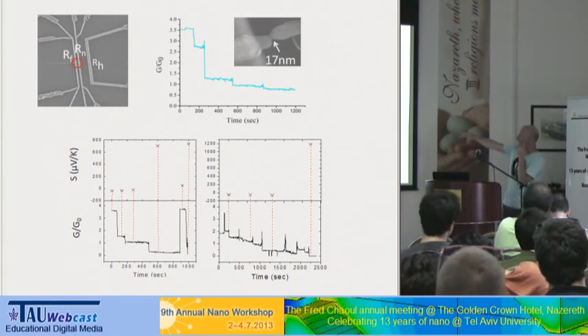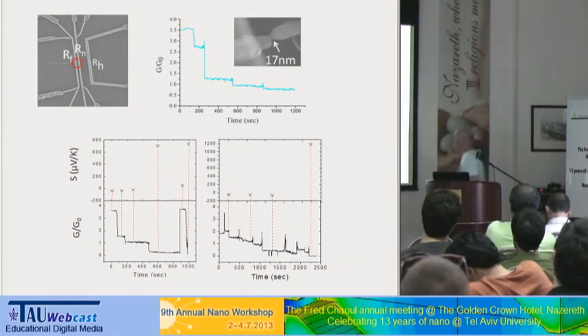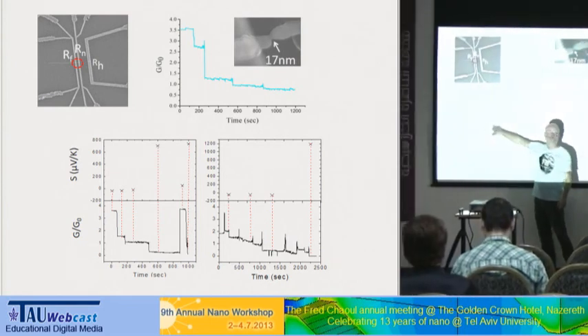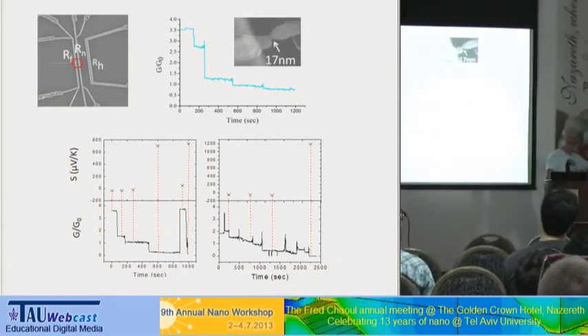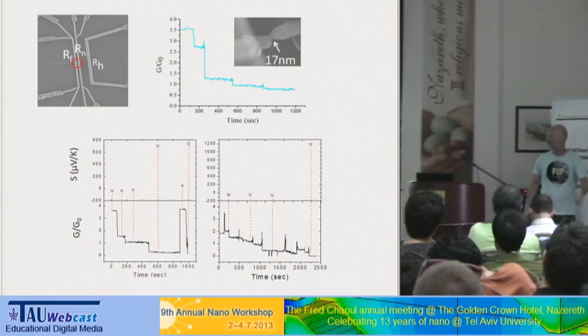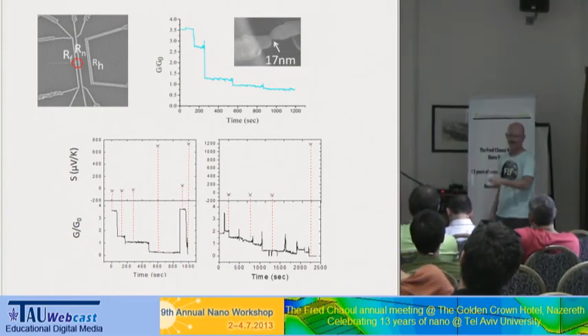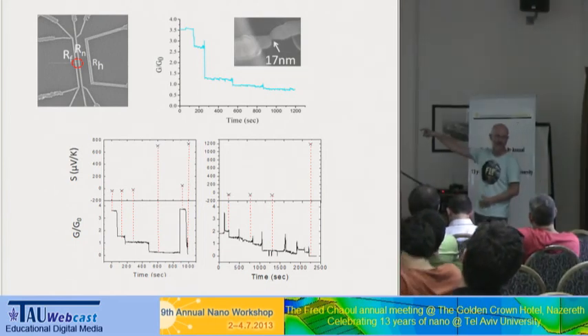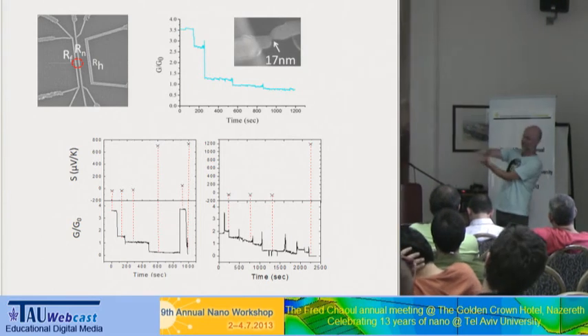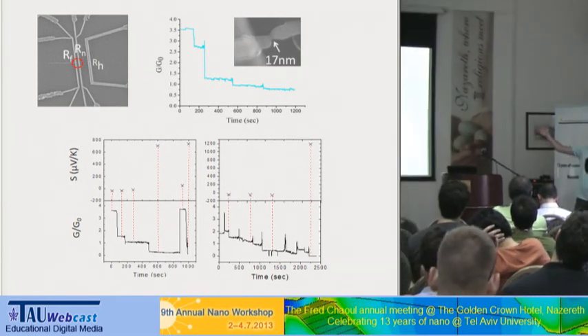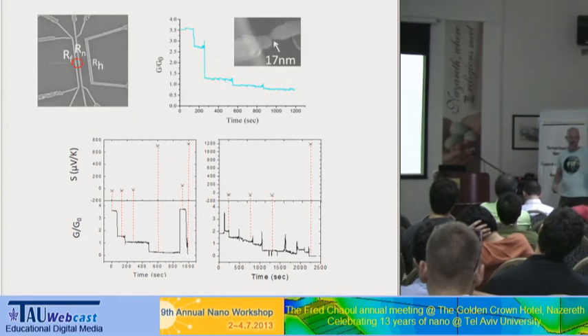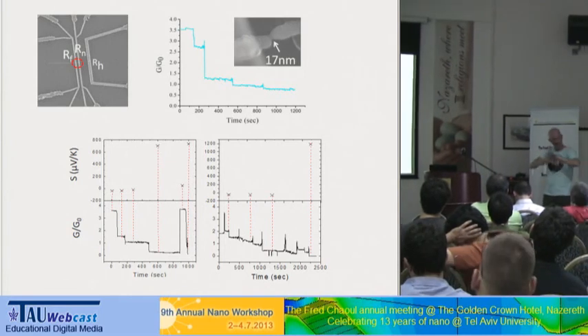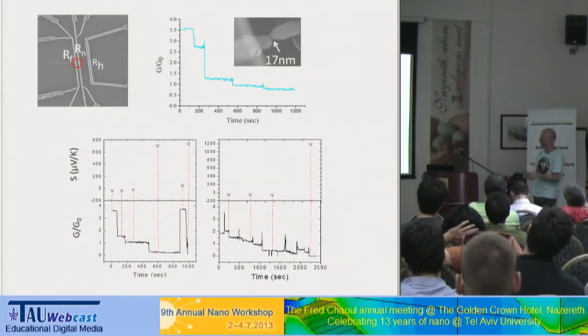The Seebeck coefficient has a sign, and here, because it was intrinsic, the electrons are the dominant carrier, because the effective mass is much smaller, so they are contributing to Seebeck here, and then once we have the gap forming, the holes are the dominating one. Once we dope it, it's going to be completely different. We need to do it in order to understand what is happening.